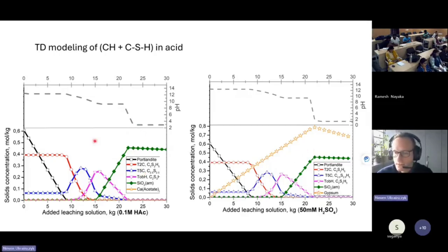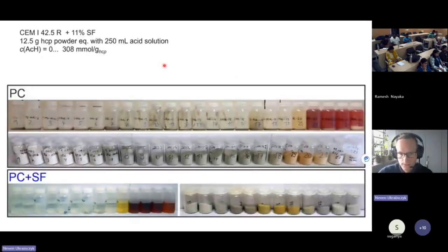The difference is that the acetic acid doesn't precipitate any protective salts, but with sulfuric acid we have gypsum precipitation. But this is again a high amount of gypsum, so there is some critical volume that then makes cracks because it wants to crystallize, it's expansive, and then you get cracks. So it is protective, yes, but it also makes your layer crack, which then again allows new acid to come in. So we did a lot of tests on thermodynamics, a lot of mixtures with different acid concentrations with Portland cement and silica fume.